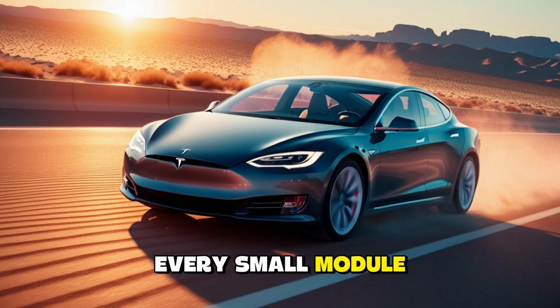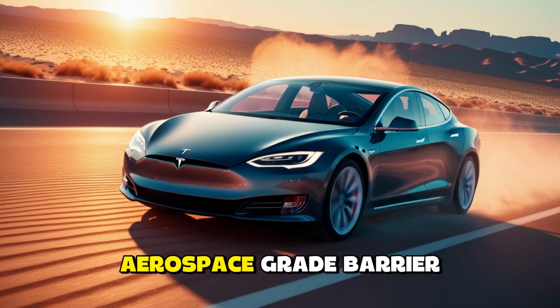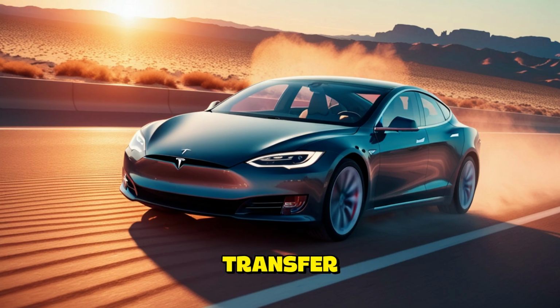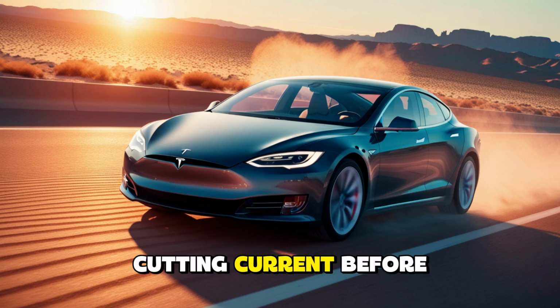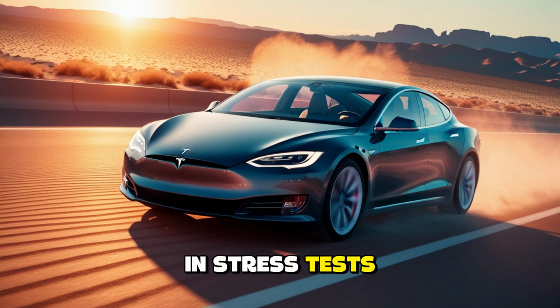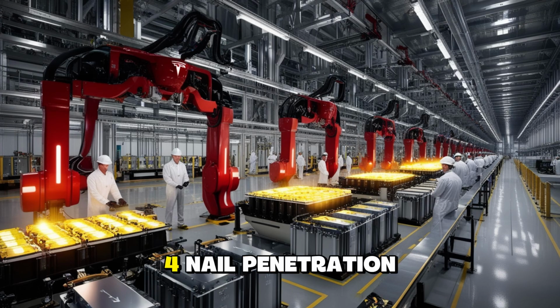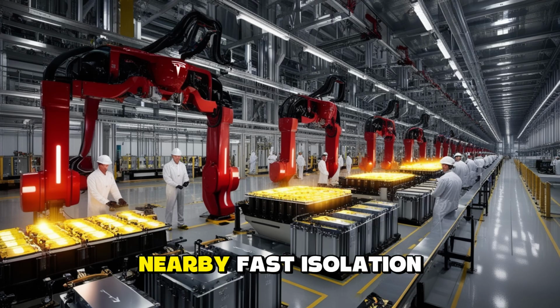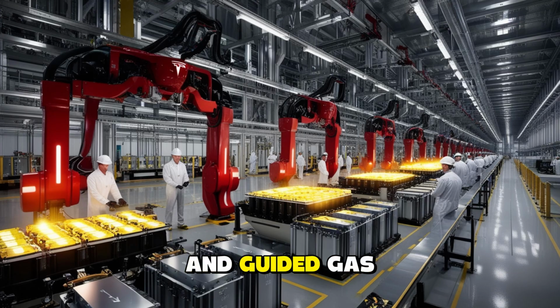Every small module inside the pack is wrapped in a thin aerospace-grade barrier that blocks heat transfer and channels vented gas through a dual exhaust spine. If one cell vents, microfuses open in just 4 to 6 milliseconds, cutting current before heat can spread. In stress tests following the SAE J2464 nail penetration method, peak temperature hit only 82 degrees C and dropped below 60 degrees C within 90 seconds, with no ignition nearby. Fast isolation and guided gas flow stop a chain reaction the moment it begins.